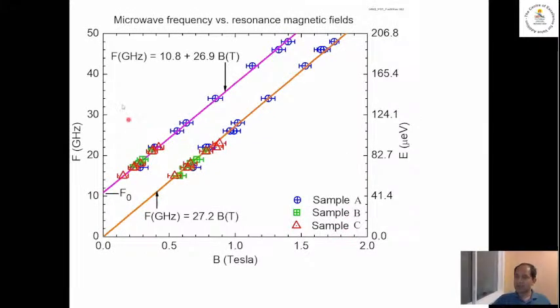What we were doing is we fixed the frequency in our experiments, and then we swept the magnetic field. So let's say we're at 42 gigahertz, sweep the magnetic field, and then you get a resonance, and then you get another resonance. That's from one of those traces. Now you can do this for all the traces, and those signals are marked here. Sample A is in blue, samples B and C are green and red. Remarkably, all these points fall on two lines. There's this orange line which heads to 0 Tesla at 0 frequency, and there's this purple line which heads to 10 gigahertz at 0 magnetic field.